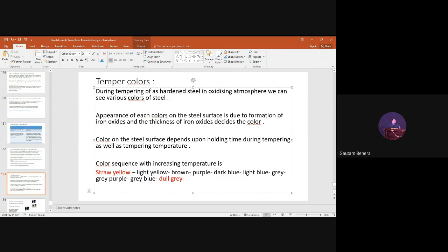What is the reason behind the appearance of these colors? The reason is the formation of an oxide film. Iron oxide will form if you do tempering in normal atmosphere without using any argon or nitrogen atmosphere. In an oxidizing atmosphere, an oxide layer will form. This oxide layer has various colors, and the thickness of the oxide layer decides what color you will see during tempering. So the more the thickness, the more different colors you will get.